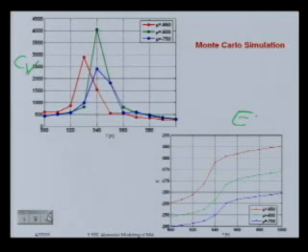But maybe what this thing does is it continues and then shoots down to that other phase vertically, so it could still be first order. So you would normally refine this a lot more. And if you really want to know that something's second order, you look at the scaling of the heat capacity with system size, and that's the really accurate way to know that something's second order. Your normalized heat capacity in a second order transition, so the heat capacity per site, scales like the square root of the number of lattice sites.